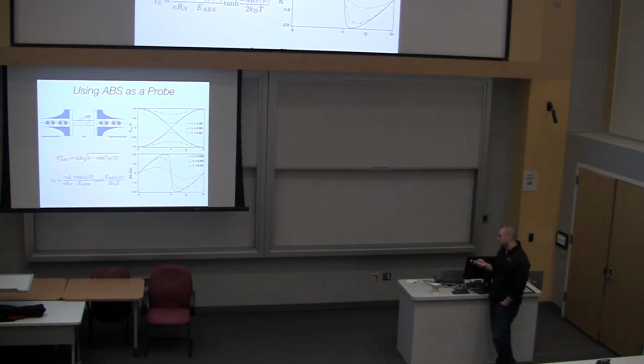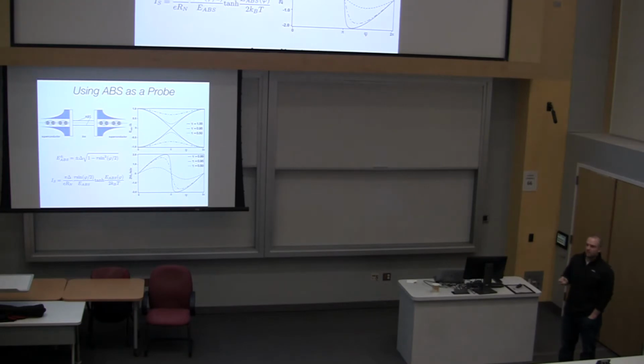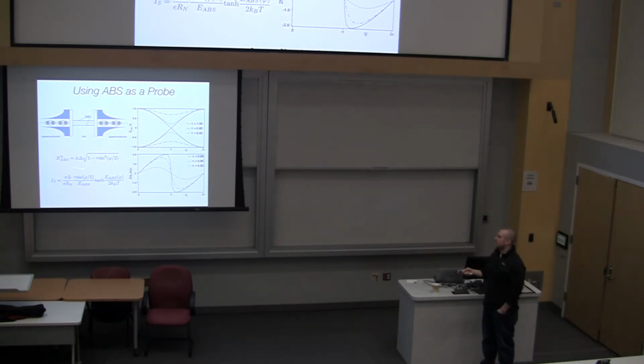And if I look at the energy as a function of this transmission probability, I see that there's a crossing at 0 energy when the transmission is 1. The transmission is often not exactly 1, but very near 1. As soon as you move away from transmission equals 1, you start to get a small gap that opens up between the energy of these Andreev bound states at a phase difference of pi. Now from this energy of Andreev bound states, I can calculate the current phase relationship. And what we see is that as tau changes, hold on.